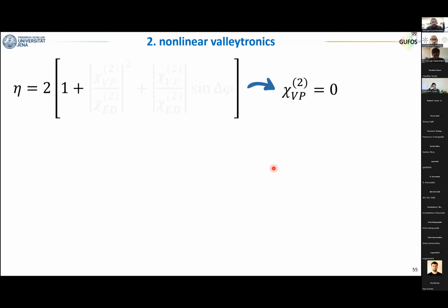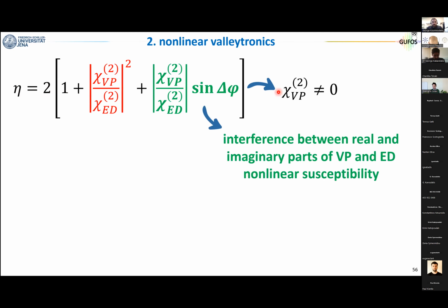Again, for this we will need a bit of algebra, but I will skip it and go quite fast. Let me only tell you that if you calculate this ratio, assuming that there is never valley polarization, not even in the circular case, so time reversal symmetry is always preserved, then this ratio, circular to linear, should always be equal to 2. And this is the assumption that everybody doing nonlinear optics in materials has used until now. Now, if you consider that the circular polarization breaks time reversal symmetry and induces a valley polarization, the ratio will be very different from 2.